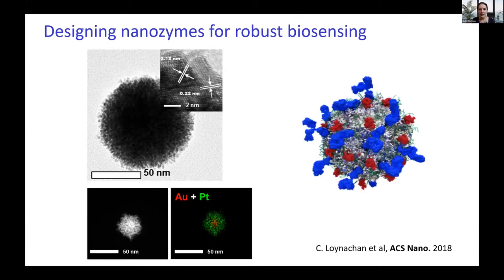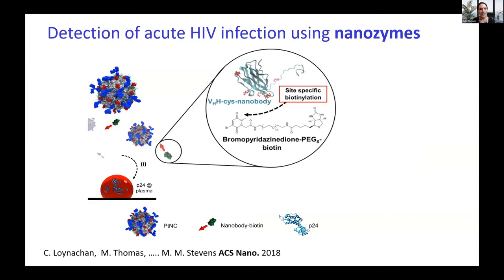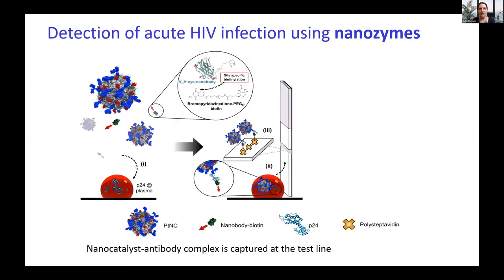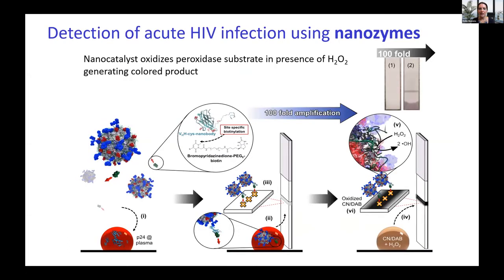And you can functionalize them with antibodies that will recognize that P24, and we then have a separate tiny binder called a nanobody that has a biotin group on it, and that can also bind to P24. So when you mix these together and then you run them up a test strip, like a lateral flow test, like you'll have seen for the COVID lateral flow tests, that biotin binds very quickly to streptavidin at the surface, and we can then capture those nanoparticles, add the chemicals, and actually get a 100-fold amplification.